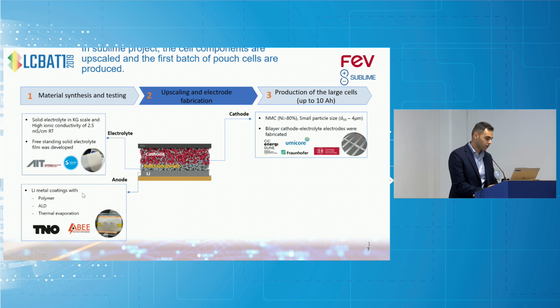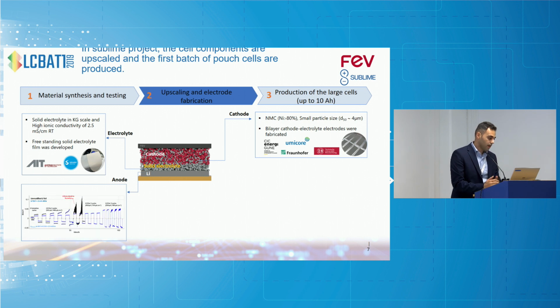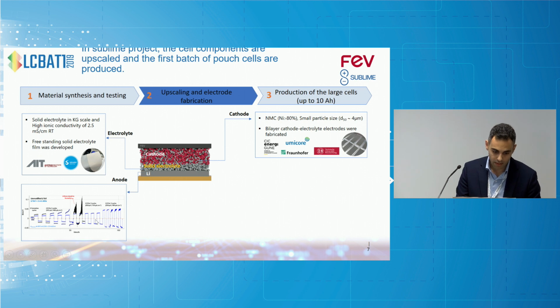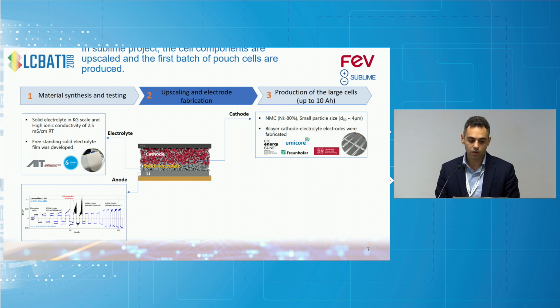On the other side, for the lithium anode, we further focus on the development of the coatings for lithium anodes, and you can see here, maybe it's a bit small, but the new coatings that were developed are stable up to current densities of around half a milliampere per square centimeter. So it is like C over 2 if you have a mass loading of 1 milliampere hour per square centimeter.